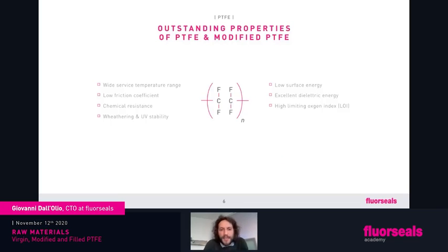So we have said fluorine is the key to the properties of PTFE, but what are the properties of PTFE and PTFE compounds? Basically, PTFE is the polymer with the widest service temperature range. It can be used from cryogenic applications, minus 200 degrees, up to 280 degrees, sometimes also higher temperature. But again, we already did the example, why can it stand such a high temperature? Basically because of the strong bond that fluorine wants to make, and does, with carbon, and also the chain that is a linear chain, very long, we will see shortly.